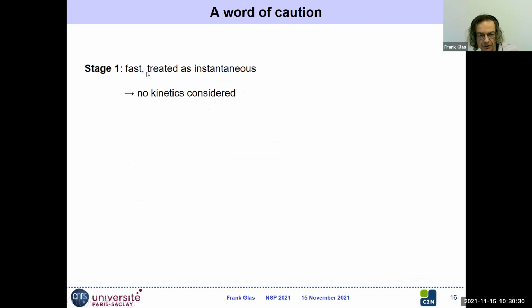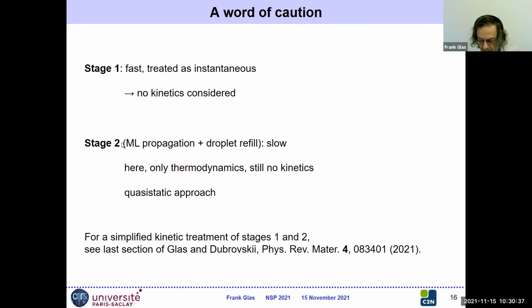Stage one was treated as fast and nearly instantaneous, so no kinetics were considered. Now I will speak about stage two, the monolayer propagation after the fast initial growth, which is slow. But today, I will only consider thermodynamics, still no kinetics. In other words, I will calculate the energy of the system for a given configuration during this stage two, and I will say that the system goes to the configuration of lowest energy.